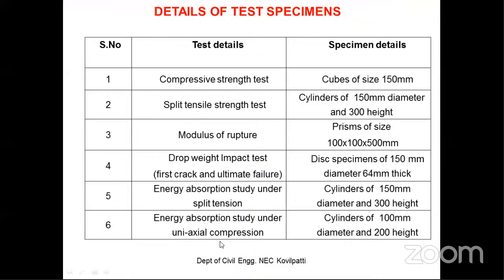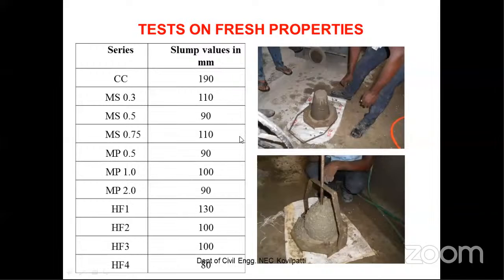And the energy absorption study under uniaxial compression has been done in cylinders of 100 by 200 mm height, and the other 3 are normal specimens. And workability is also a very essential parameter in FRC development. The normal slump cone test is recommended, and you can see that it is ranging only between 90 to 190. So the incorporation of the fibers will affect the workability, but nowadays we are adding PC based admixtures, so it is not at all a big problem.